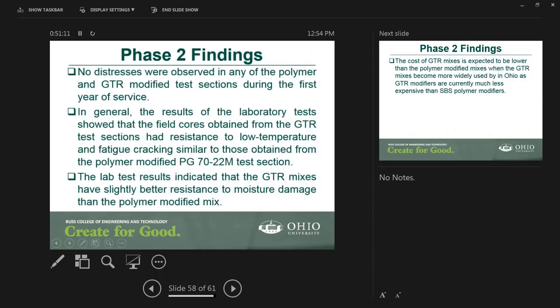So to summarize, so far there are no problems in terms of performance. For the two sections, we did not really observe any distresses after, I would say, a year and a half of service of the GTR mixtures. They performed very similarly to the polymer modified. The lab testing also indicates that they have a similar performance in low temperature cracking and fatigue cracking resistance as compared to the polymer modified.